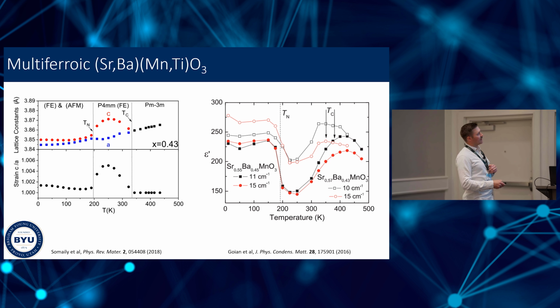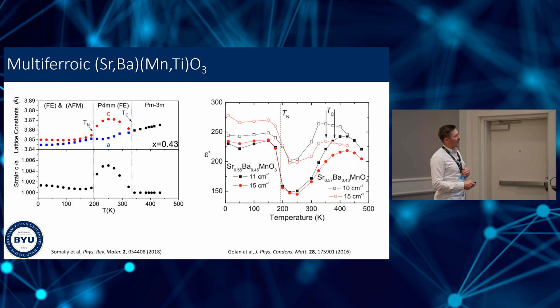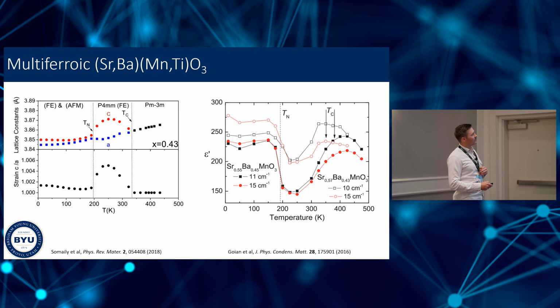So here's some of the early evidence of multiferroic behavior in this material. We're seeing here the A and C lattice parameters, all right? So in the cubic state, of course, A is equal to C. But then below the ferroelectric Curie temperature, A and C split, okay? And then at lower temperature, the antiferromagnetic order kicks in.